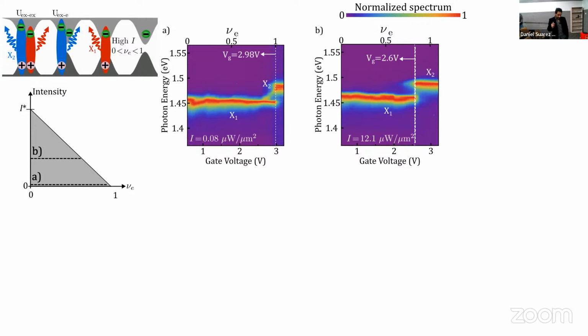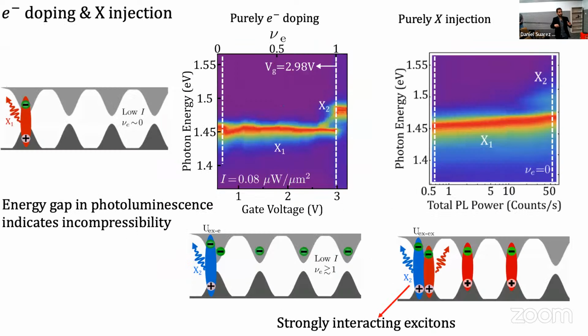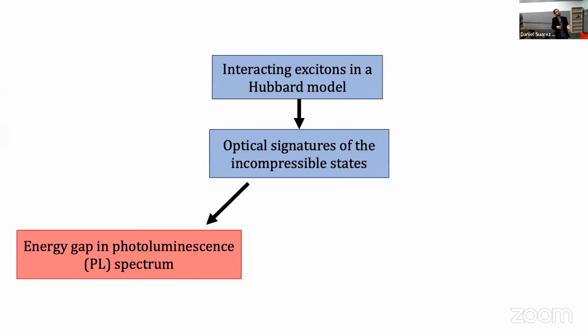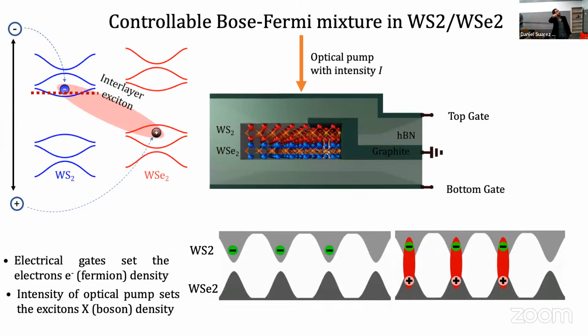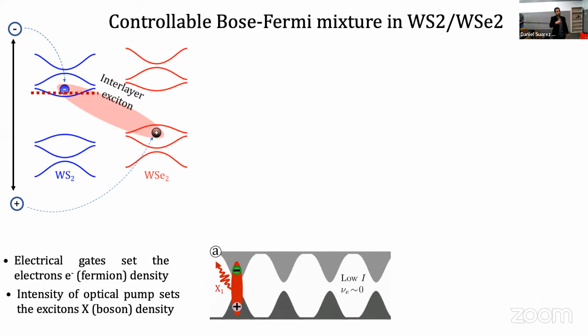Because that looks like what you're doing. Yeah, so in that regard, there is a constraint in where we put the excitons, which comes from the band alignment. So we can dope the material, but we can only put electrons initially, in this case, in here. You see that the conduction band of the tungsten disulfide is lower in energy than the tungsten selenide. So I cannot choose what band to dope, at least not in this device. That's one constraint, and that is also the reason why the interlayer exciton forms exactly like this. We cannot form the opposite interlayer exciton, because of how the conduction bands align with each other.